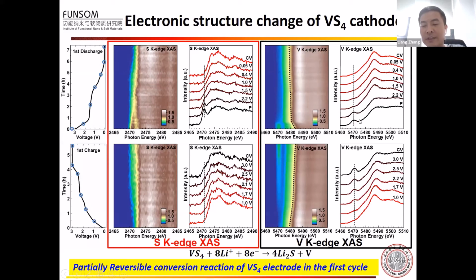The pre-edge feature is related to the 1s to 3d transition. And during the discharge process, the pre-edge feature gradually disappears. And in addition, the main absorption edge shifted to lower binding energy, indicating the reduction of vanadium.